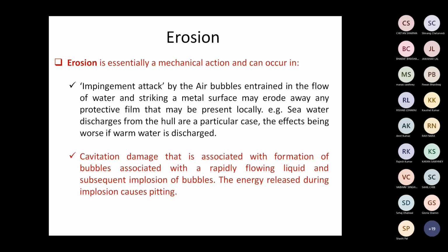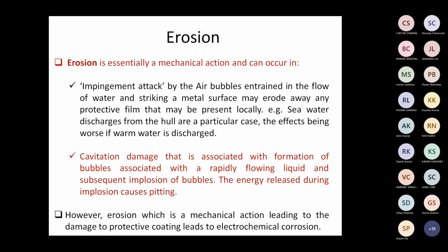Cavitation damage is associated with formation of bubbles in a rapidly flowing liquid and subsequent bursting of those bubbles, called implosion. The energy released during implosion causes the pitting or the erosion of the metal. So the causes of erosion could be impingement attack by the air bubbles, or cavitation damage by the implosion of the air bubbles which are created. However, erosion, which is a mechanical action, leading to damage of protective coating. Once the coating is damaged and the metal is exposed to the environment, obviously it can set in the corrosion.